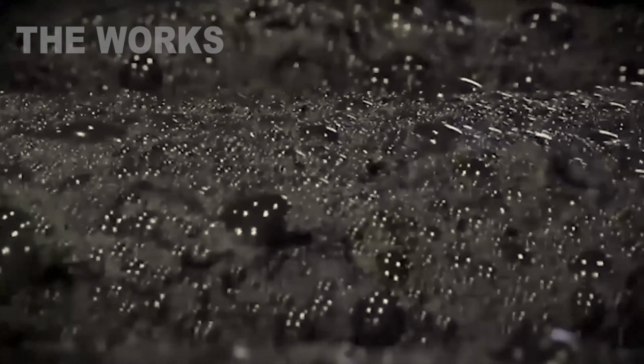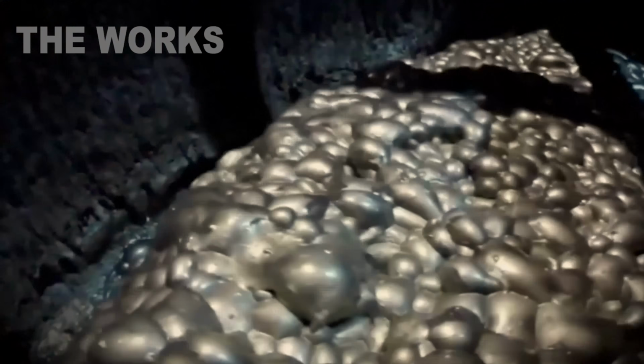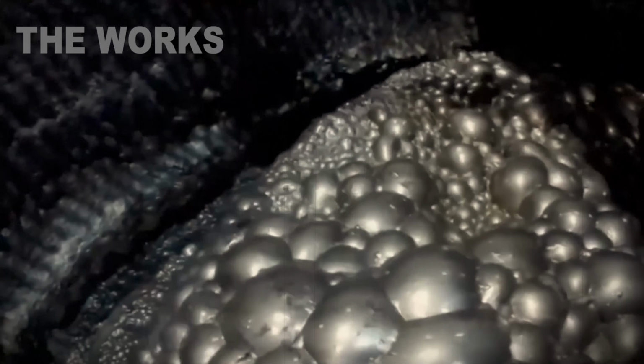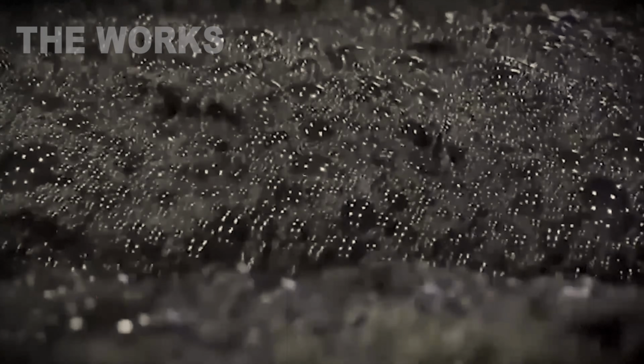The waste rock sinks to the bottom. Scrapers skim off the foam. That's copper concentrate with 23% copper content. One flotation cycle pulls out 88 to 90% of the copper from the ore.